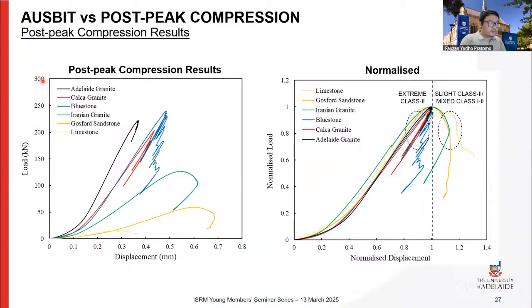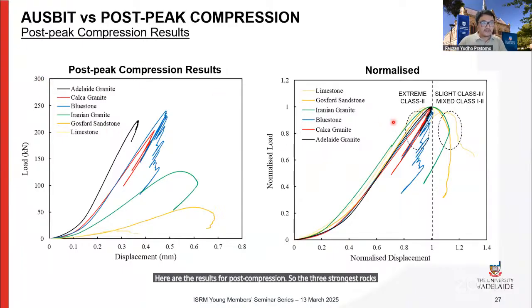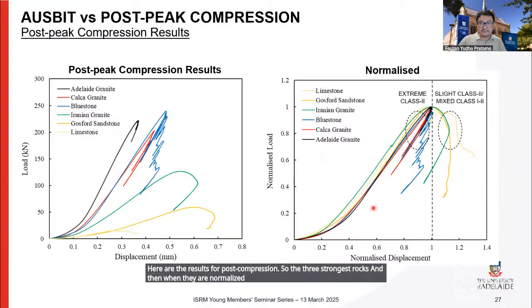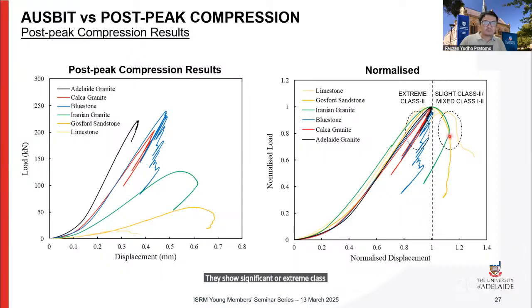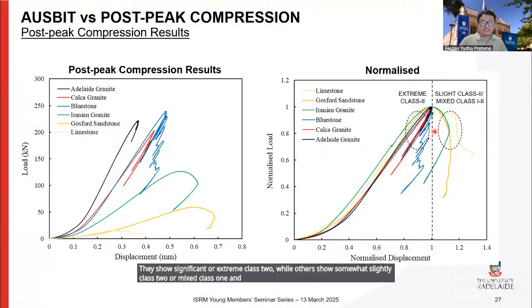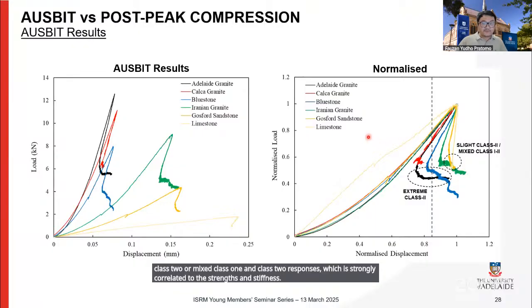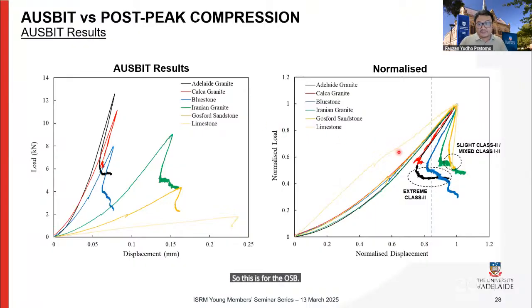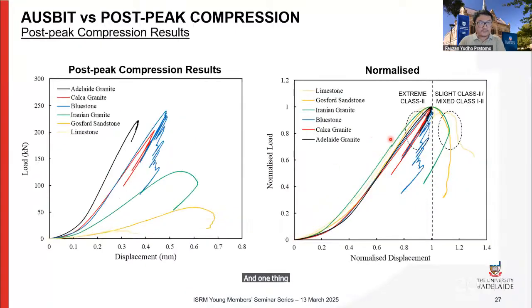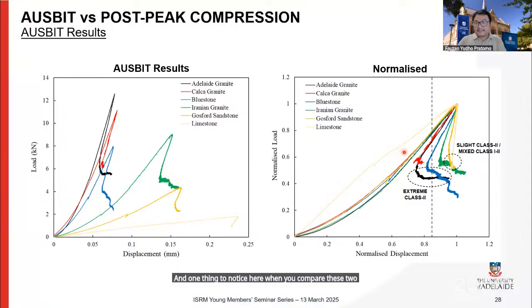Here are the results for post-peak compression. The three strongest rocks, when normalized by the maximum load and displacement, show significant or extreme class 2, while others show slightly class 2 or mixed class 1 and class 2 responses, which is strongly correlated to the strength and stiffness. So this is for the AUSBIT. We can also see the extreme class 2 and then the slight or mixed ones. And one thing to notice when you compare these two is the sharper snapback in tension, which means greater energy dissipation.